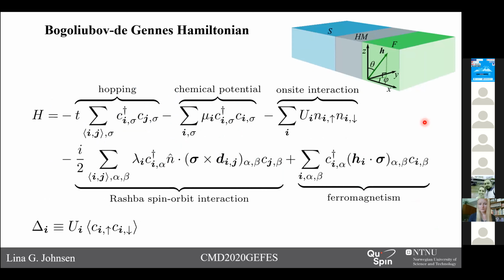So to approach this problem, we use the Bogoliubov-de Gennes framework. And the good thing about this is that we can combine any combination of atomically thin layers of materials. And also, since this is a ballistic limit framework, we can model the crystal structure of the lattice. So we considered a 3D cubic lattice and this Hamiltonian,